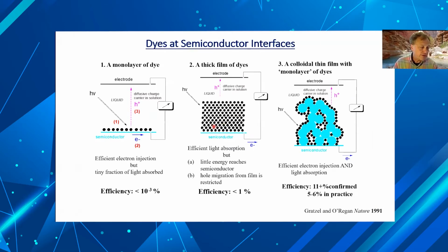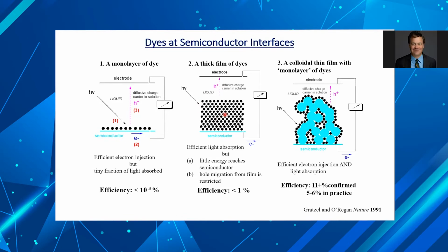One of which is that you can create an excited state, say right here in the middle of this layer of film, and it doesn't get to the interface in order to transfer an electron into the semiconductor, a process we often call charge separation. Said differently, the exciton diffusion length of that excited state is shorter than the penetration depth of the light into the film, so you don't successfully convert light to electrical energy. The dye simply relaxes through radiative and non-radiative means.